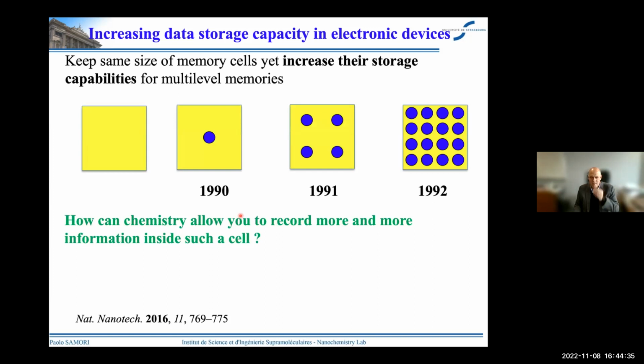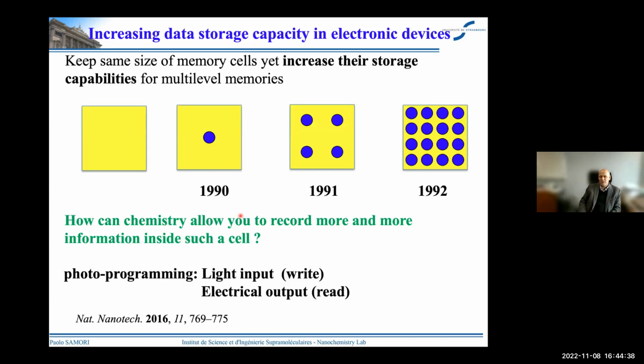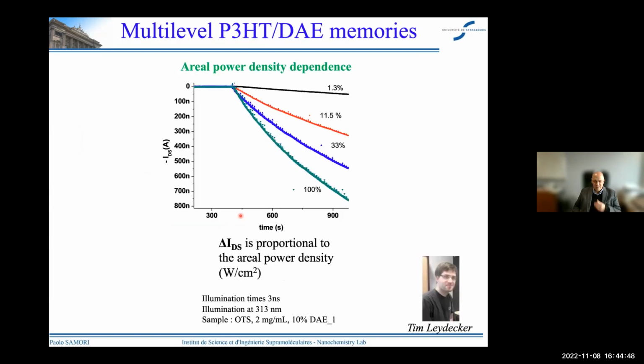The way to do that is, for example, to write with light and to read electrically. So to use two orthogonal stimuli for the writing and for the reading. That is something that we realized could work with Tim Leydecker, who was doing his PhD in our group. And we had actually the very same type of blend, the P3HT diarylethene, I showed you before, to make an optically switchable transistor. And what he noticed is that depending on the areal power density of the UV light he was using, he could observe a different type of decrease of the current through the junction upon the illumination with UV light. And in particular, if you use very short pulses, in a few nanoseconds, you could minimize this kind of effect.